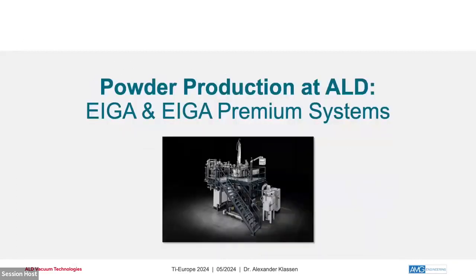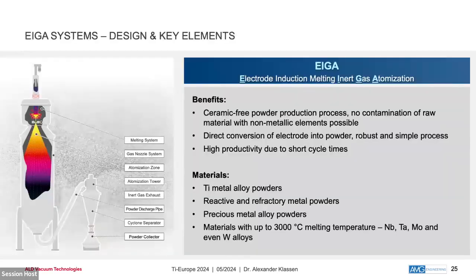So first, an EIGA system for powder production. Where are the benefits of this system? The action takes place up there where the melting chamber is and the nozzle is located. Down there you have the atomization tower where the molten powder falls in, and the collection and sieving systems. The benefit of this system is that you atomize without having contact to a mold or a die. So you can produce powder without it taking up other materials like ceramic particles or the like, and have a high purity of your material. So it's very advantageous for reactive materials like titanium in this case, or also for refractory metals.